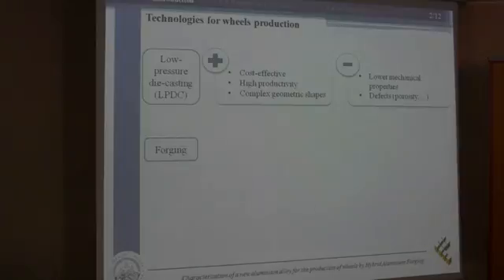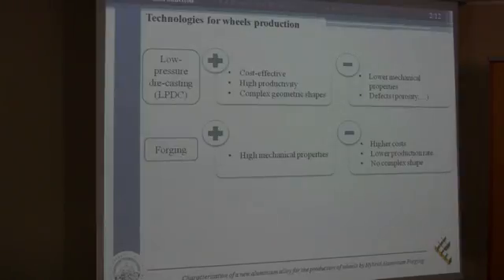The main technologies for the production of light alloy wheels are low-pressure die casting and forging. Low-pressure die casting is a cost-effective process which can ensure high productivity and the possibility to produce wheels with complex geometric shapes. On the other hand, the mechanical properties of cast wheels are not as high as those of forged wheels, and this is indeed the most important feature of this other process. Forged wheels cannot have such a complex shape as cast wheels, and also the process requires higher cost and so a lower